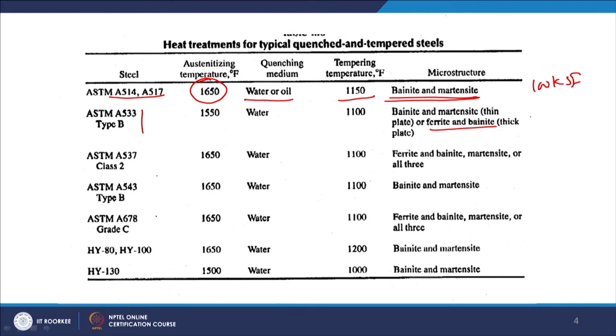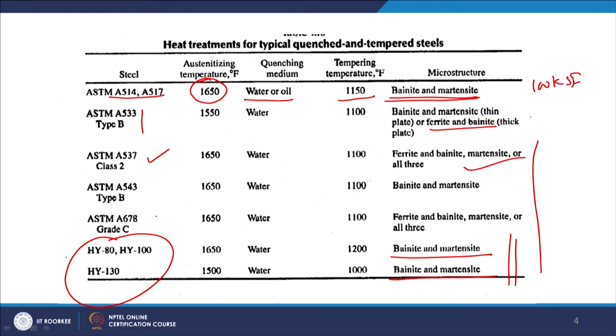Other steels, when subjected to different types of heat treatments, will have different microstructures, as we can see from these steels. Most of these steels in QNT conditions are supposed to have bainite and tempered martensite, and as per the grain size of these steels, the relative fraction of these microconstituents will give different combinations of mechanical properties. So, more critical in these cases, much higher yield strength is realized through the combination of the same phases by controlling the relative fraction of these microconstituents.